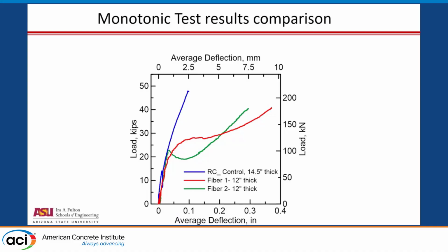Now, the different samples can be compared. Your original design is shown in blue, which is the reinforced concrete. Extremely stiff system. We can go up to about 220 kilonewtons, about 48 kips, and it's really stiff, less than 0.1 inch deformation. The one with only fibers is going through, first of all, your load capacity, your design level is about 10 kips. Whereas what we do is we go up to about